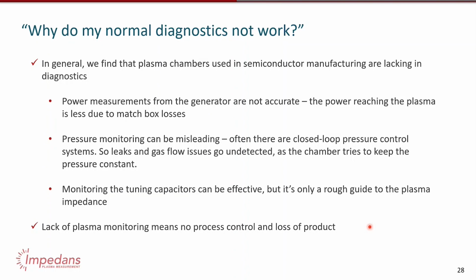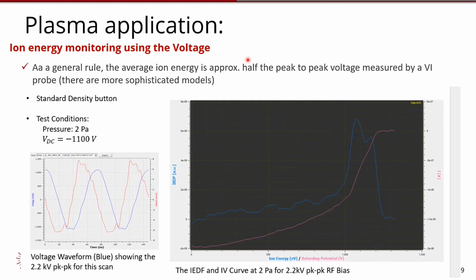Right, so let's start off with the simple plasma applications, okay, before we go to the complex ones. I mentioned earlier on that you can actually know a lot about the ion energy impacting the wafer on an RF biased electrode just by looking at the voltage. As a general rule, the average ion energy is approximately half the peak-to-peak voltage as measured by a VI probe. Okay, so I have a real example here.